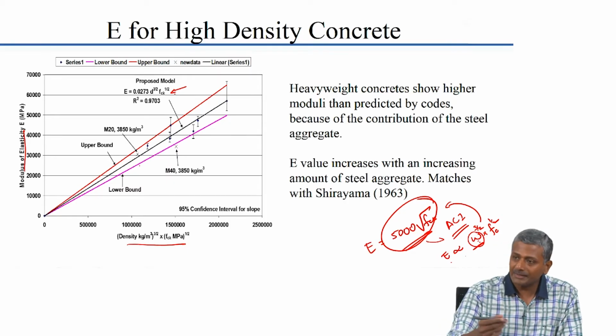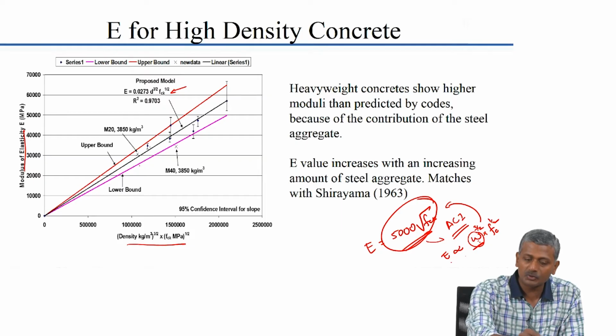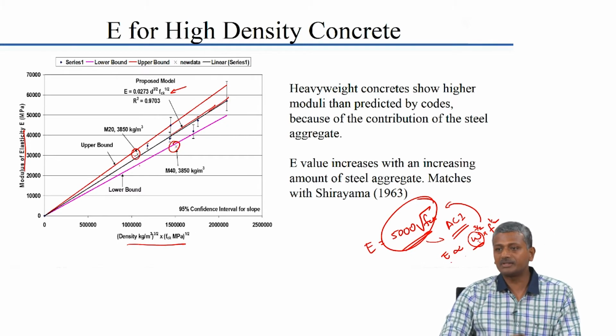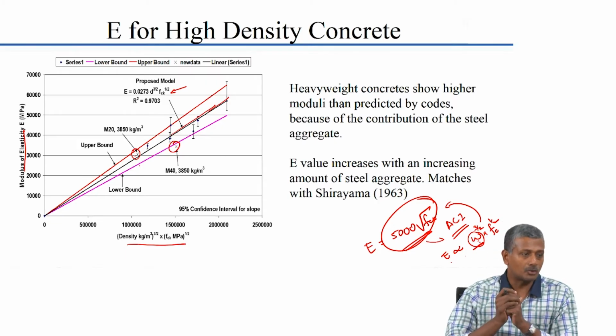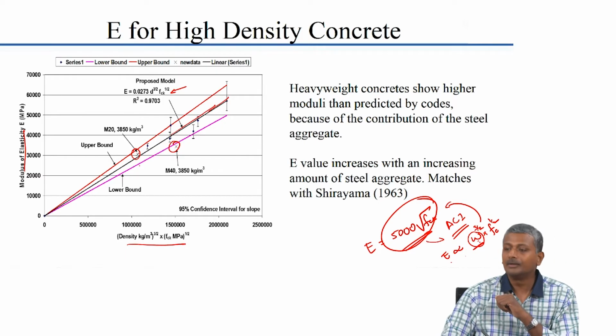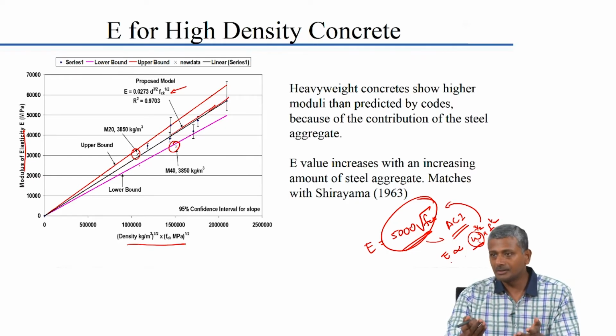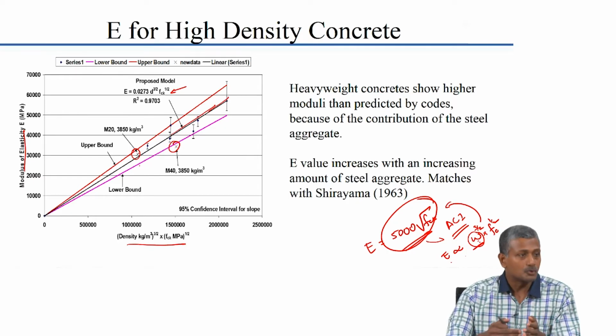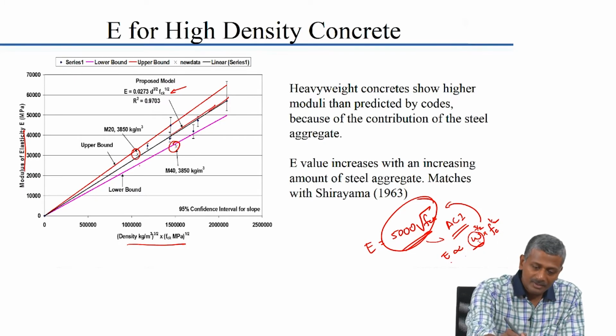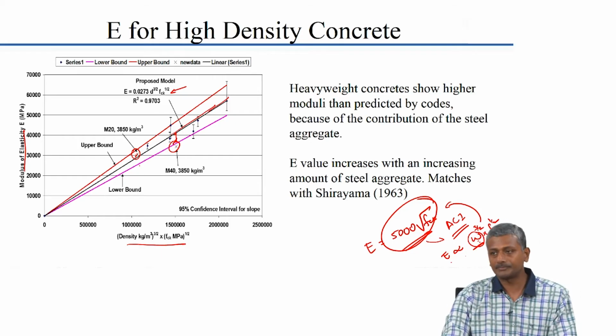We had done this design with certain types of mixes which led us to this straight line relationship, and then later we also made some random mixtures which were not part of the original study and saw whether they were following this relationship properly or not. These two mixtures that I marked in red are the ones that were additionally cast, which were not from the same set of mixes that were used to get this relationship. We wanted to see whether they were satisfying this relationship. Within certain error, you can see that these are satisfying the straight line relationship also.